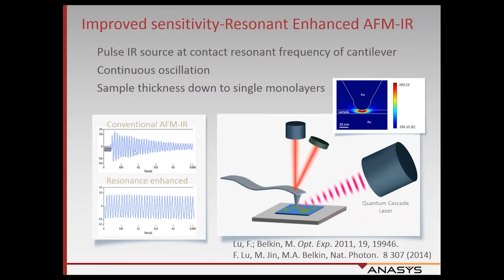We also recently, in collaboration with Mikhail Belkin at the University of Texas, developed a technique called resonance-enhanced AFM-IR, where we synchronously pulse the laser with the contact resonance frequency of the cantilever, and that lets us achieve very, very high sensitivity, including that monolayer sensitivity that I mentioned earlier.